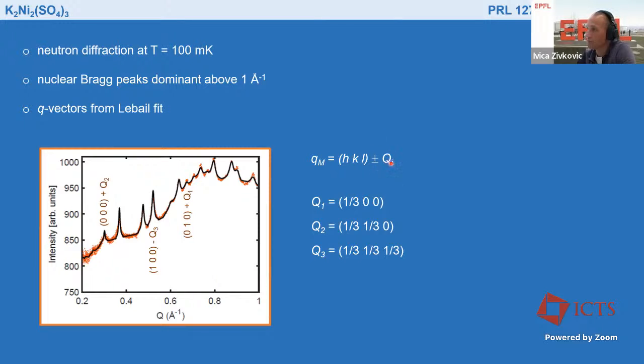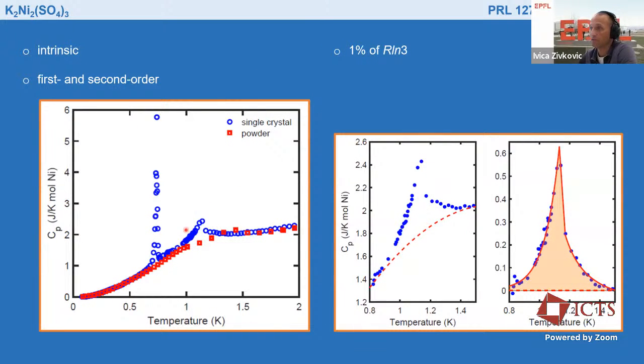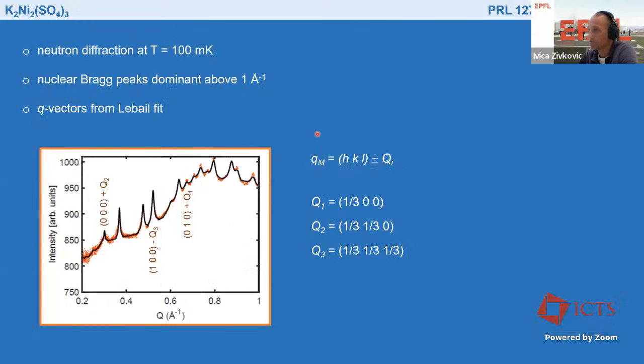So the Q vectors here, as satellites of nuclear Bragg peaks, indicate that the wavelength of this ordering is larger than the unit cell. So in this context, we believe that this represents a second order transition into an incommensurate structure, and then a first order transition into a commensurate structure, which then hits this 1/3 Q vector.